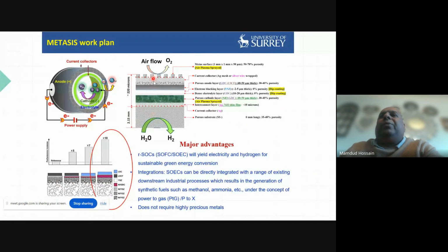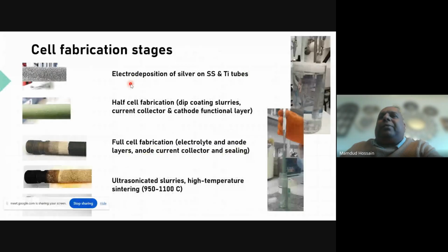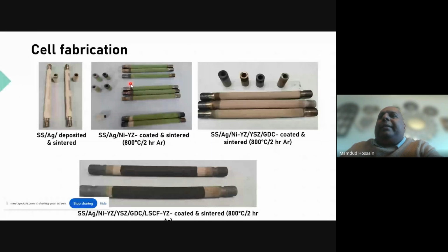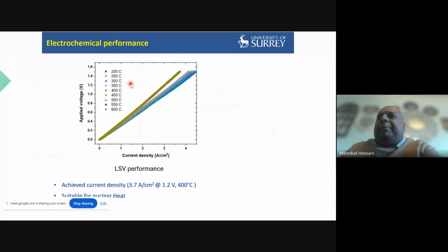We managed to thin out cathode, electrolyte, anode. We have adjusted their porosity gradually, and we have multiple layers. On top of that, we have a microstructure on the anode surface, what we call meta surface, and that surface also creates better oxygen electrochemistry and movement of oxygen away from the surface. So we are very pleased with our achievement, experimental achievement here.